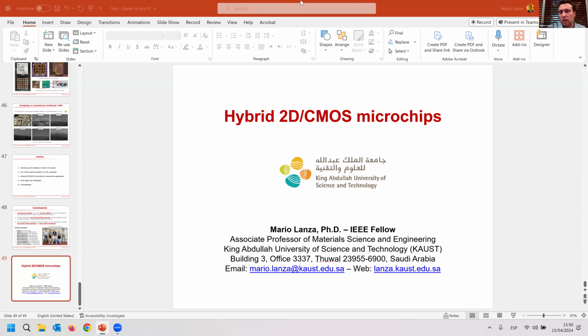switching voltages. However, we could not make a systematic study because we don't get reproducible quality of boron nitride over different batches. We are now starting to do this with the new samples. But I will say that we have managed to make memristors from almost every boron nitride by adjusting these four parameters.